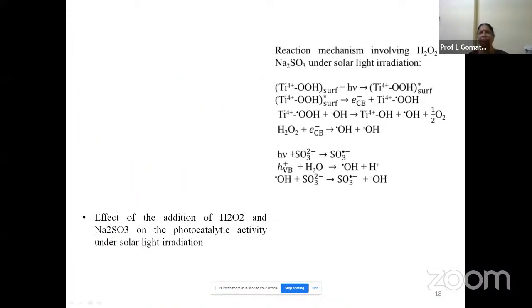The reaction mechanisms taking place when I have added H2O2 or Na2SO3 are shown in this slide. The peroxo radical forms a complex kind of structure at the Ti4+ site, and this complex absorbs the light and gets excited, and the excited molecule gives the electron. That is the mechanism shown here in the first set of reactions. H2O2 also absorbs under UV light, and very little H2O2 absorbs visible light. But even then, hydroxyl free radicals and OH minus are formed.